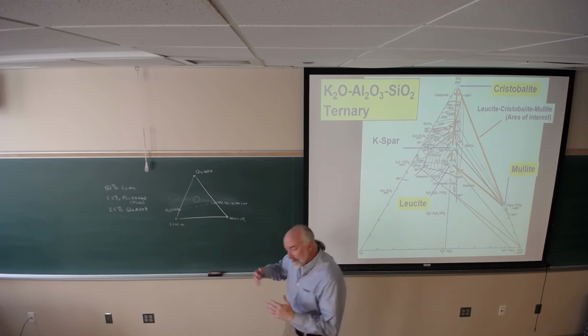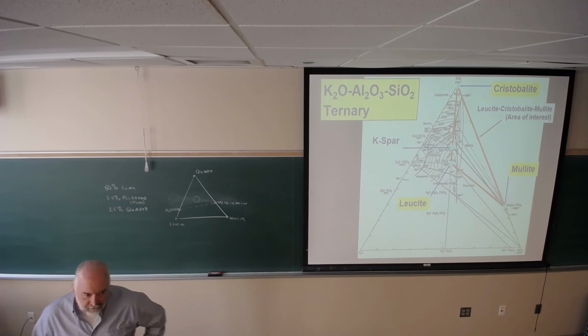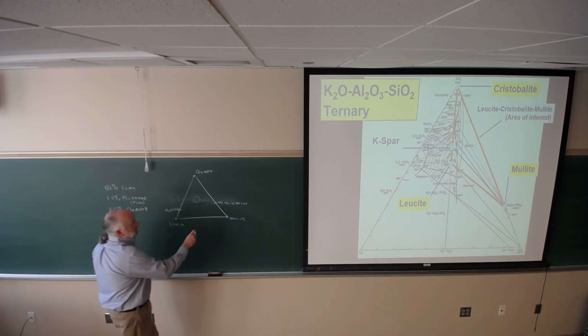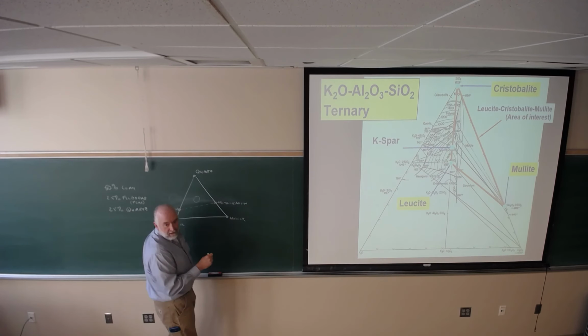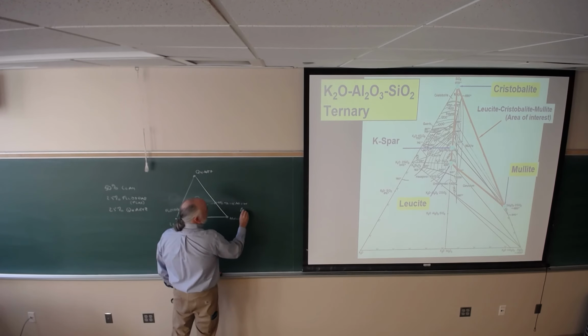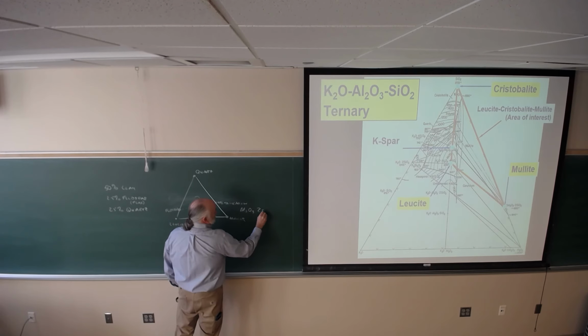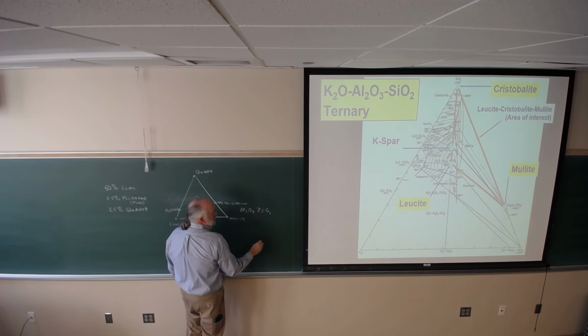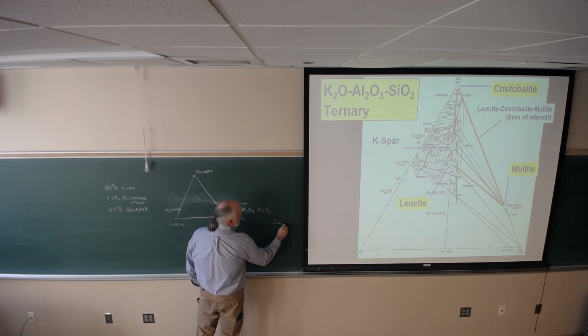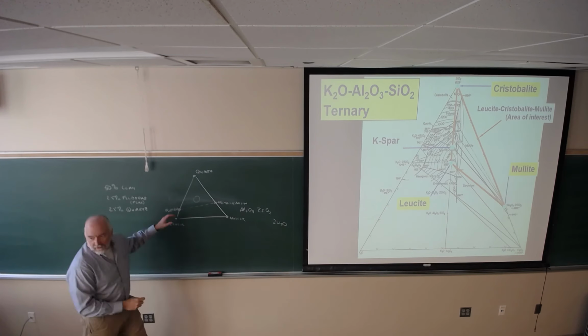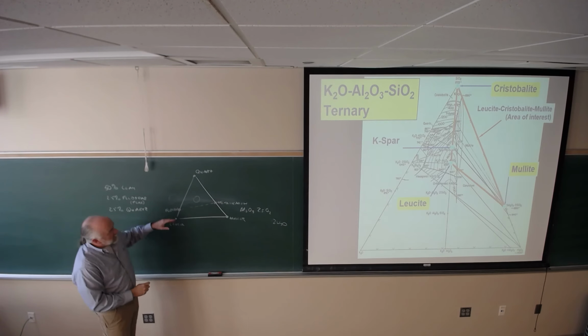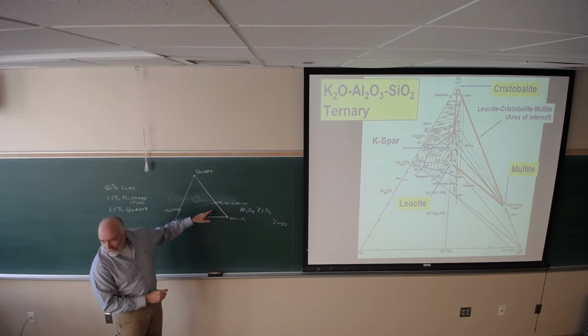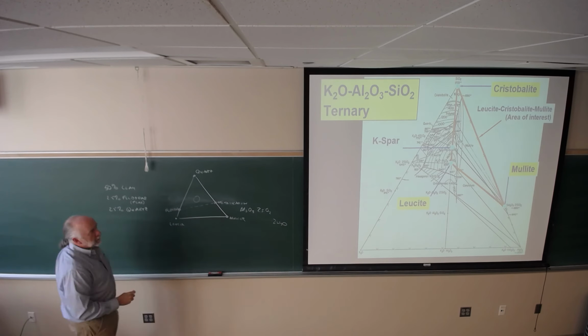And the reason that metakaolin isn't on the diagram is because it actually is the decomposition product of clay. So this actually has a composition, which is this. Okay, and if it was clay, it would have on the end 2H2O, but we don't have water on the diagram, so we can't represent it that way. So essentially, if I heat up my clay and lose the water, then I can plot it in the phase diagram.